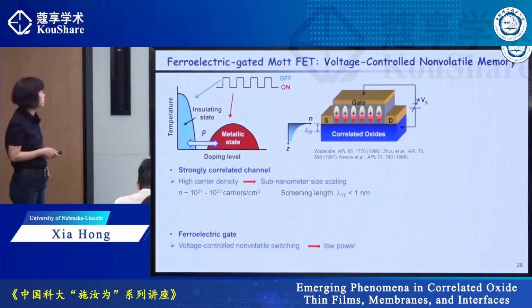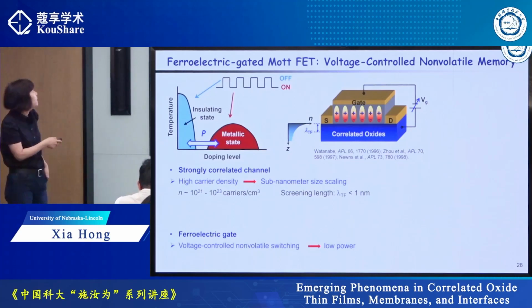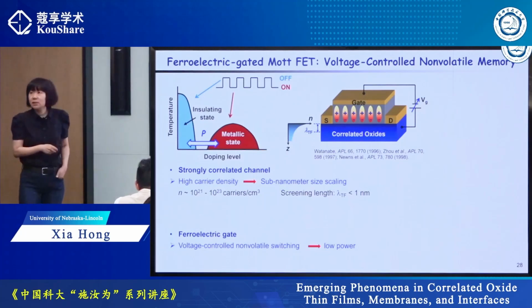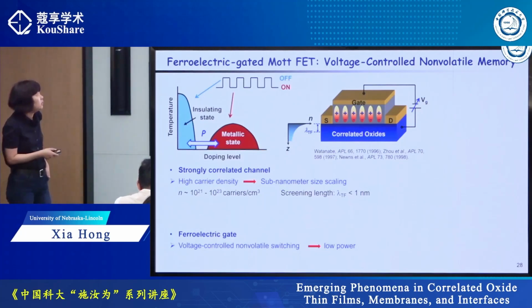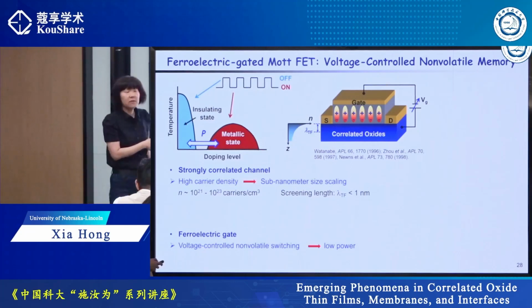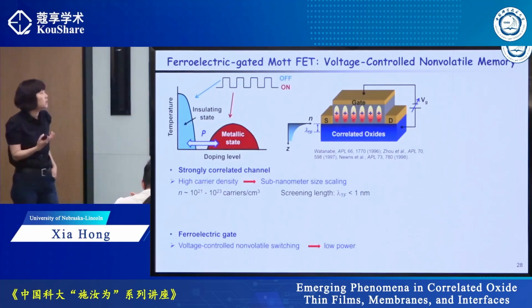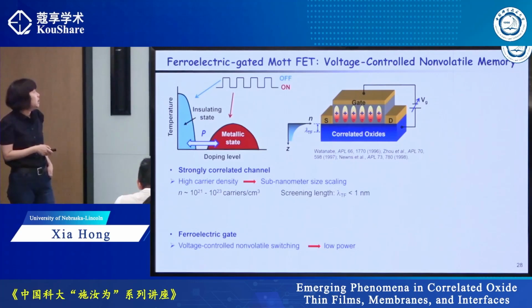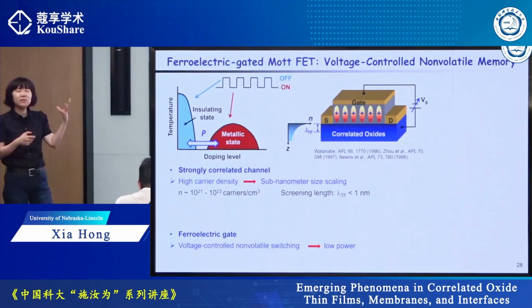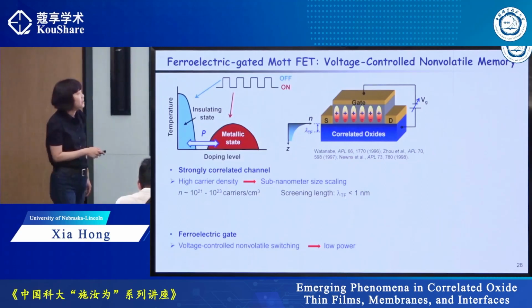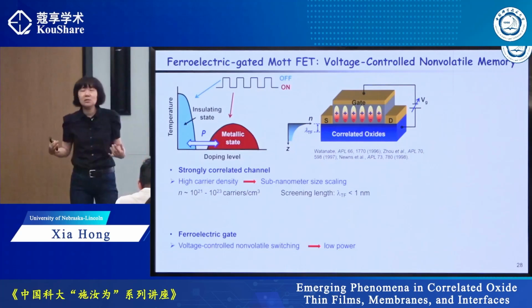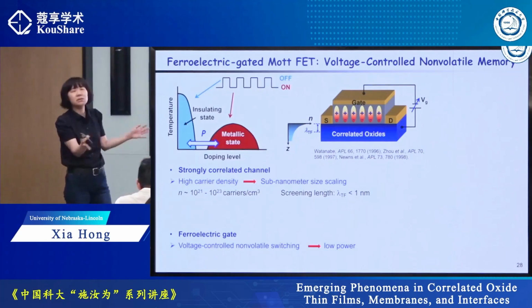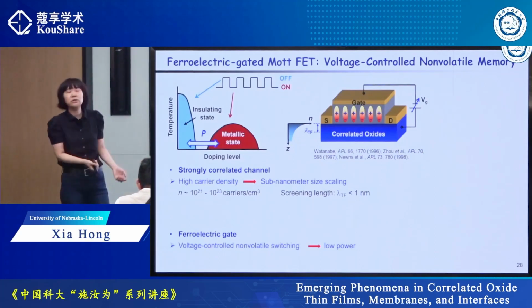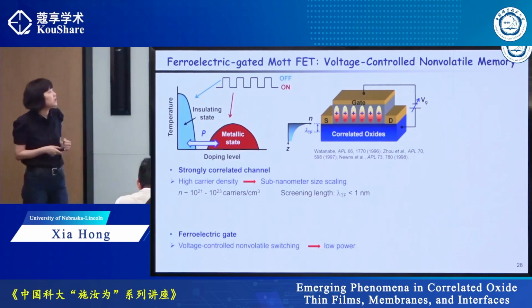It's a Mott transistor. You work with a Mott insulator that you can tune from insulating state to metallic state using carrier density. So what if we use a field effect to induce this insulator to metallic change? The advantage is the Mott insulator has intrinsically very high carrier density in the on state. That means its screening length is smaller than 1 nanometer, so you can make a channel smaller without a short channel effect. You can turn the channel off.